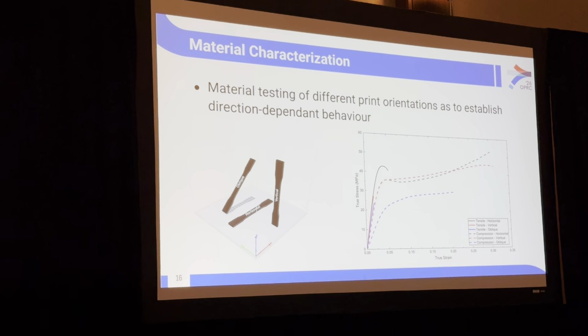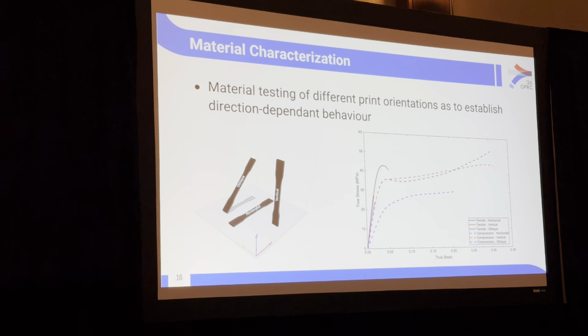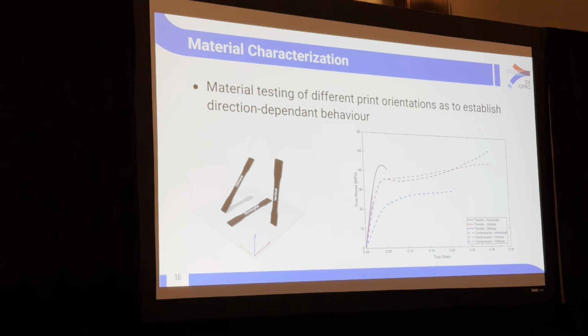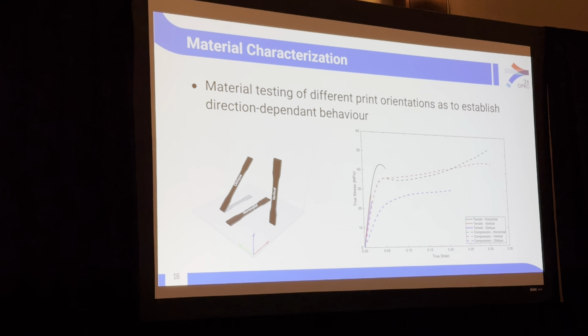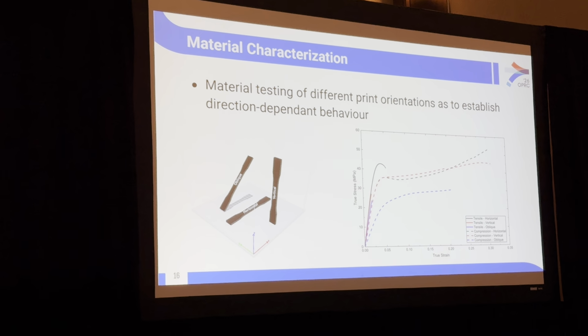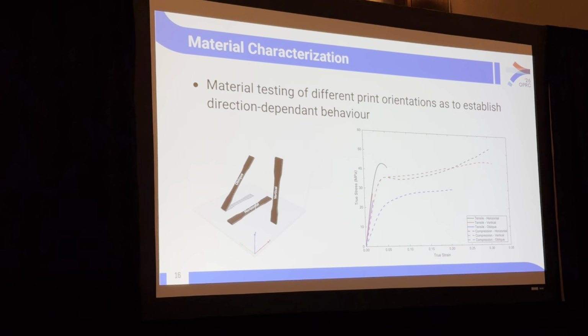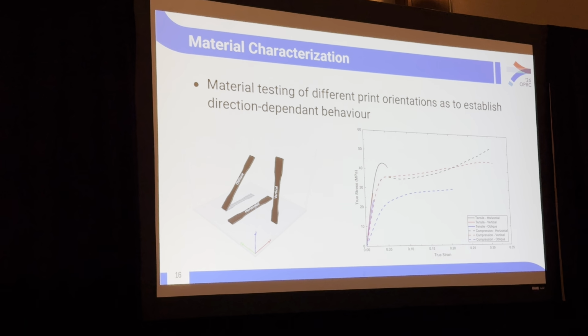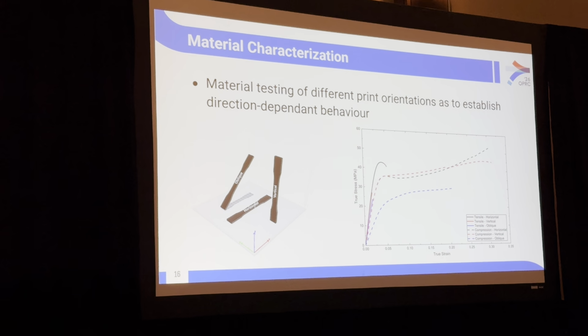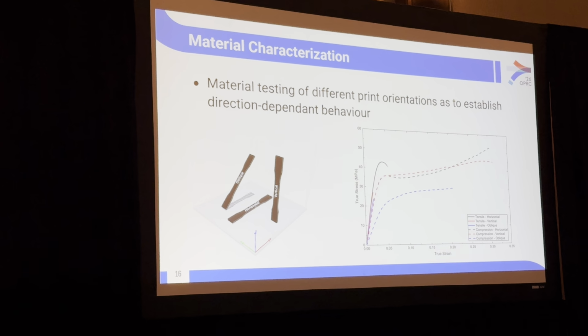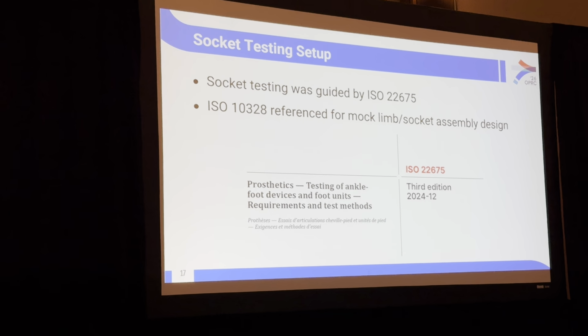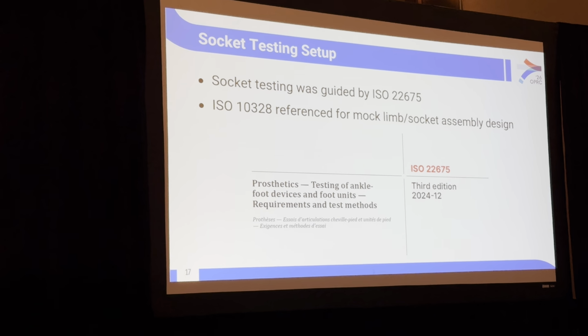And I won't go into much of what this plot is, but what I want to highlight here is that we see in the different colors here shown in black, red, and blue that there is different material behavior between those different print orientations. But we also see, when we compare the solid lines to the dotted lines, that there's a difference in material behavior between the tensile and the compressive behavior as well. So this brings us into our socket testing setup.